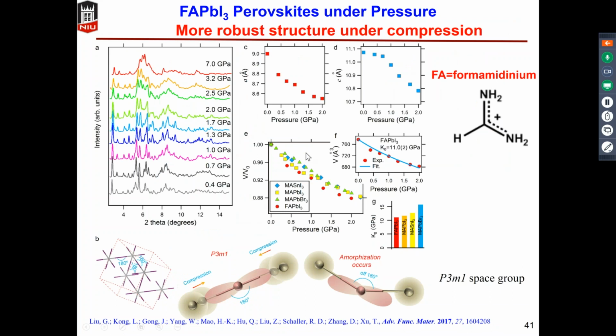And as I said, because there's a kink in the lead iodide bond in MAPbI3 that caused the phase transition at relatively low pressure, 0.4 gigapascal, we chose another perovskite, which used formamidinium as the cation, and this material has a relatively straight lead iodide bond, and so we can compress it all the way to 7 gigapascal without phase transition. And during this process, we find that the lattice constant continues to decrease.